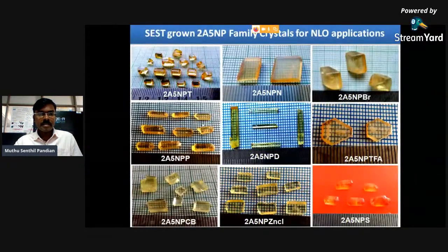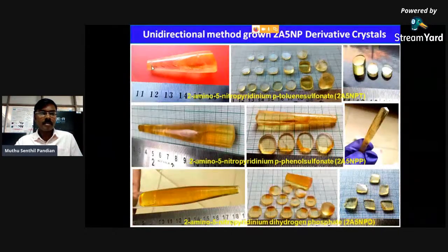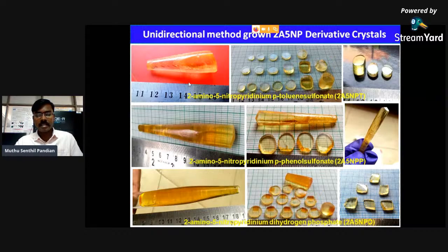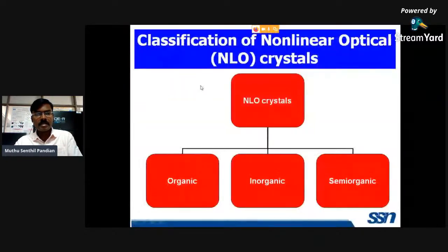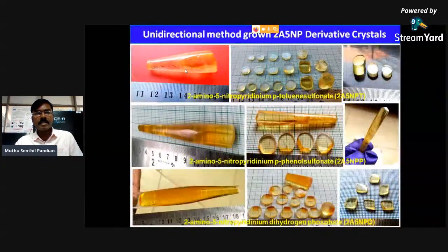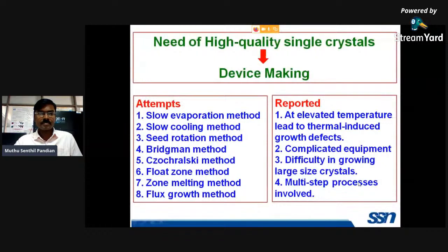So what we have done is we have selected one of these crystals and we have mounted it at the bottom of the ampoule and we have grown the crystals. These crystals can be grown by this SR method using this glass ampoule. This is another 2-amino-5-nitropyridinium derivative single crystal for nonlinear optical applications.